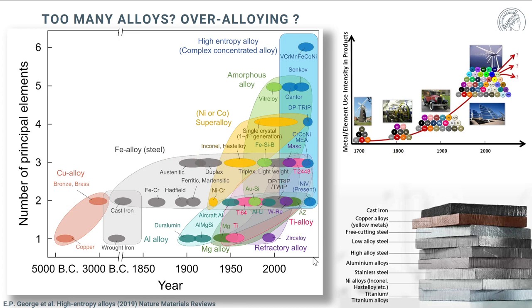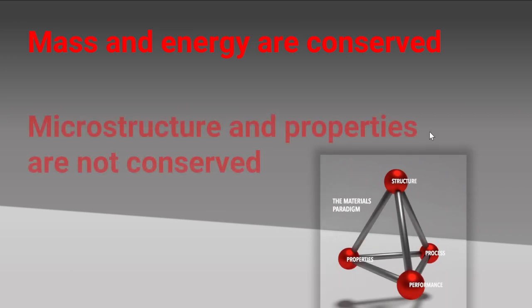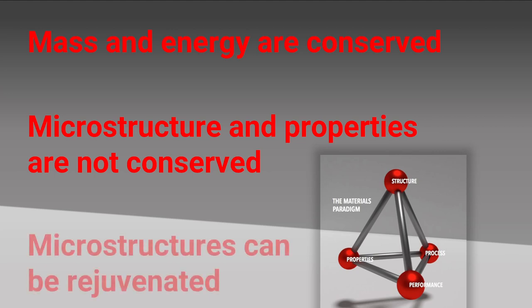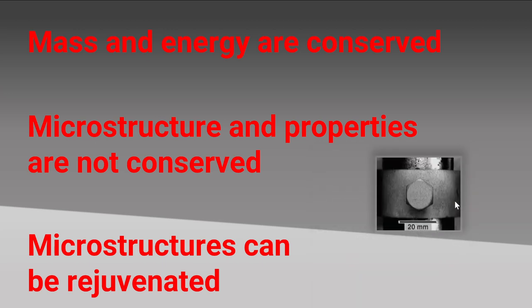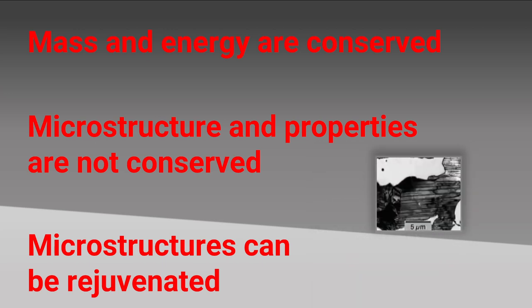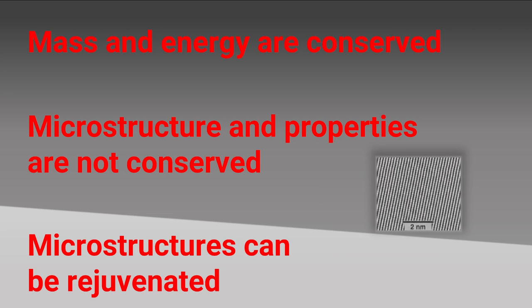And that is a trend which is maybe not entirely compatible with the field of sustainability, unless you do so to gain or produce properties that you cannot achieve by other materials. So principally, that shows us that, of course, mass and energy are conserved quantities, but microstructure and properties, the main cornerstones of our field of material science, are not conserved. And that is a very good message, because by microstructure design and heat treatment and forming processes, we can create new microstructures and can rejuvenate established microstructures, as you see with this little movie.